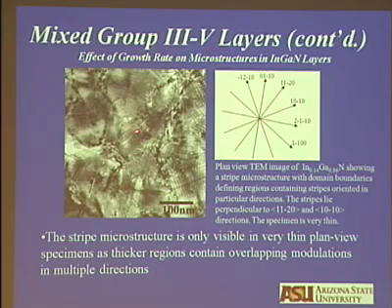And you see the dark stripes are indium-rich. We haven't proven it, but dark stripes are indium-rich regions and the light stripes are gallium-rich regions. And if you look at it, the volume fraction fits very well. And also look at the crystallography. The directions normal to these stripes tend to lie along one of these directions.